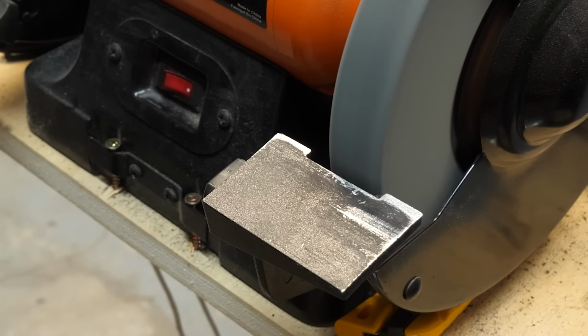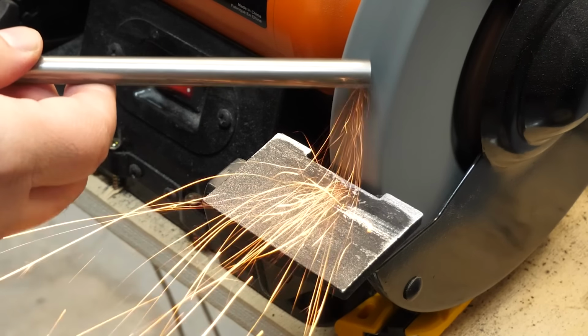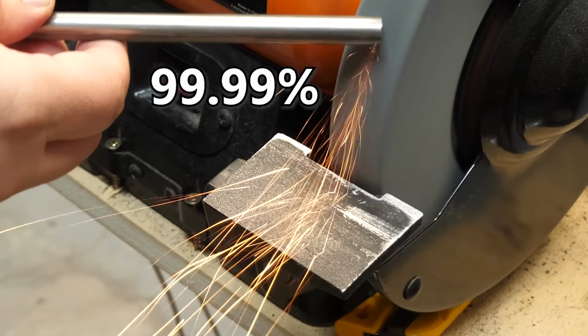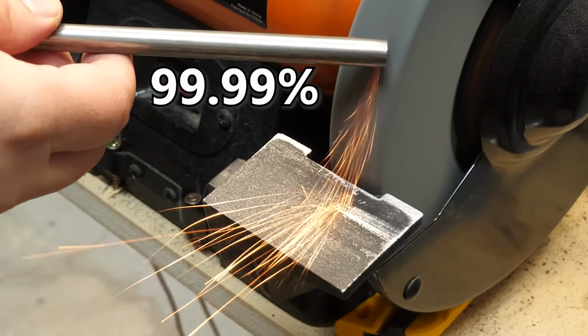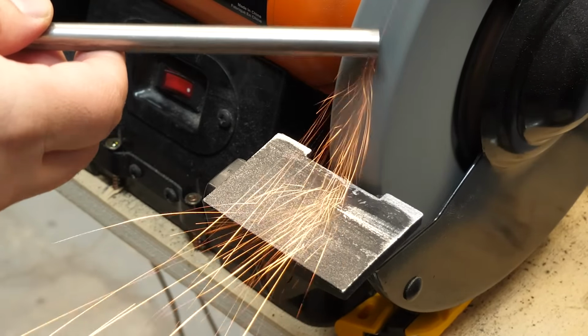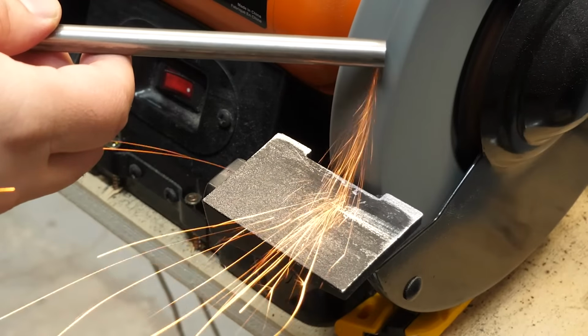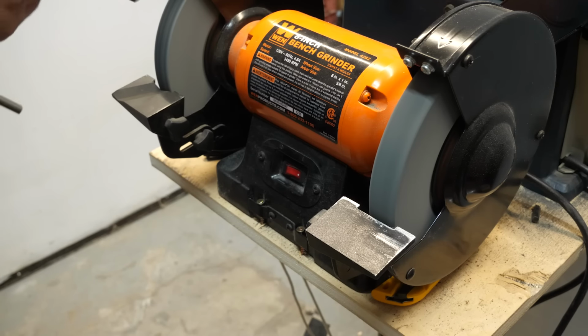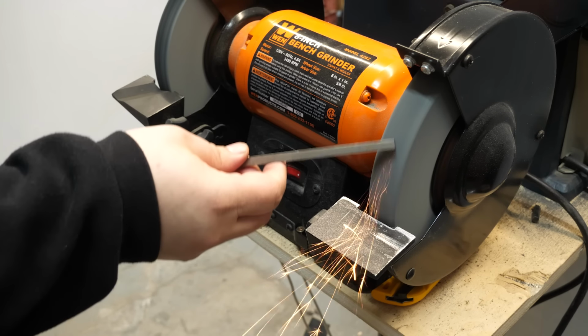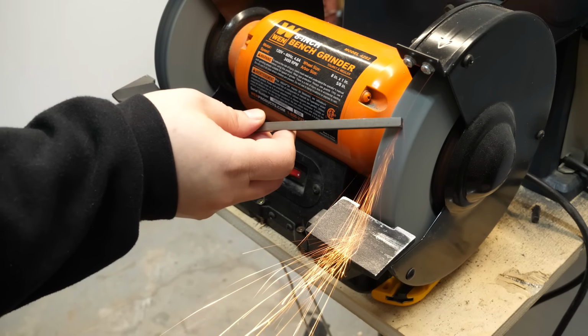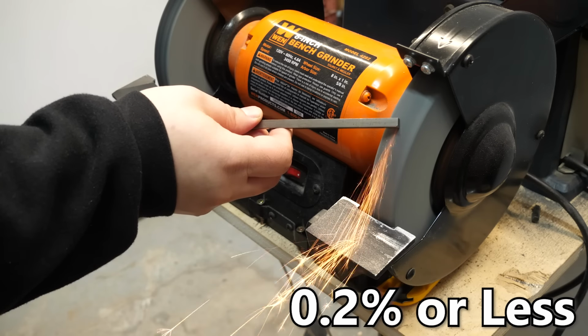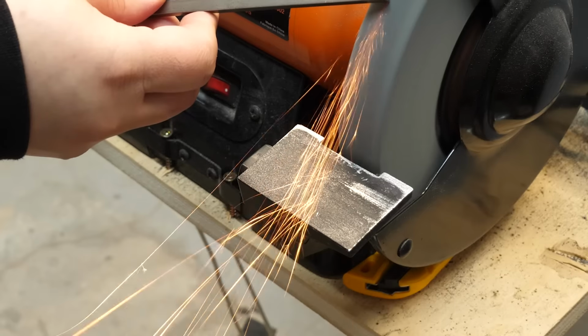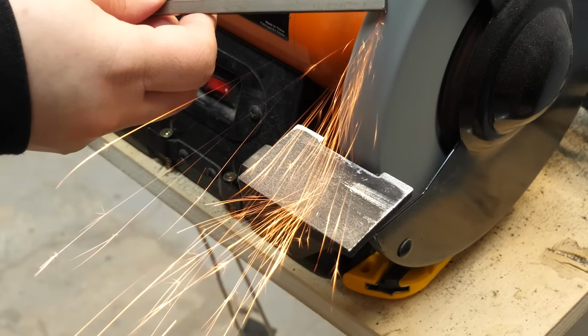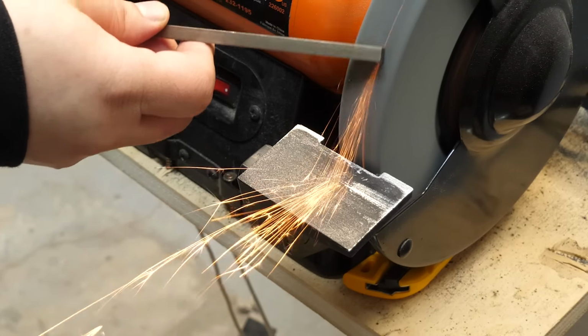The other test to see if we've made steel is to touch these to a grindstone. When it's pure iron, here we're using a piece of 99.99% electrolytic grade iron, we get long thin sparks of the pieces of iron burning mid-air. But as the carbon percentage increases, the sparks change. Mild steel, which has around 0.2% carbon or less, sparks with a bit more pizzazz, and you can see little explodey tufts at the end of the sparks.